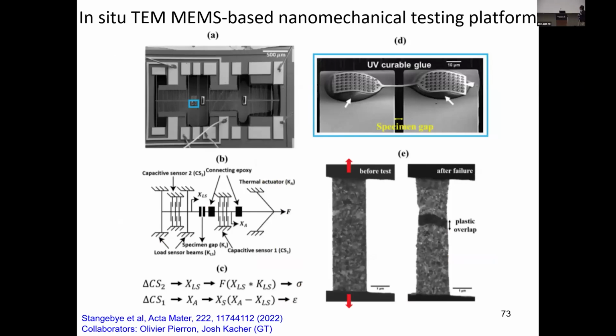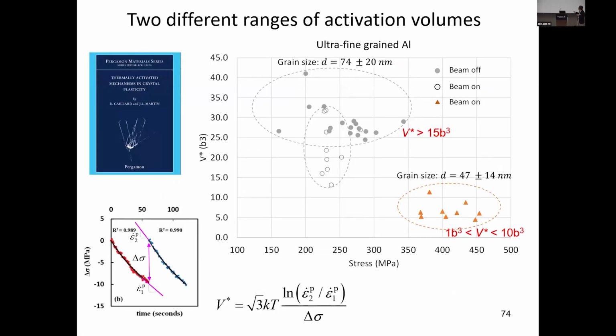We are not only satisfied with the observation, so through a DOE BES project, my collaborator and I used this in situ MEMS-based nanomechanical testing platform inside the TEM. We can quantitatively measure the stress-strain behavior of ultra-fine grained metals and thin films, so that we can measure, for example, the activation volume and activation energy. This enables us to study the deformation kinetics to determine the rate controlling steps, either at the grain boundary or within the grains. And we can also use the TEM to directly visualize the deformation process and couple with the in situ atomistic simulation to identify the rate controlling mechanisms as a function of grain size, temperature, and strain rate.